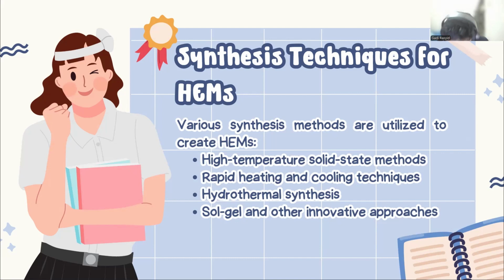The oxide particles of 6 nm were uniformly supported on carbon nanotube scaffolds, with the carbon nanotubes also acting as microwave absorbers. If the basic structure of a conventional laboratory furnace is maintained but allows samples to pass rapidly through the heating zone, heating and cooling gradients can be precisely controlled. Spray pyrolysis is an example where small droplets of precursor solution are generated and passed across a high temperature area. Under the constraint of surface tension, droplets evaporate and shrink, ultimately forming spherical solids, which prevents the size increase of product typically seen in traditional pyrolysis processes.